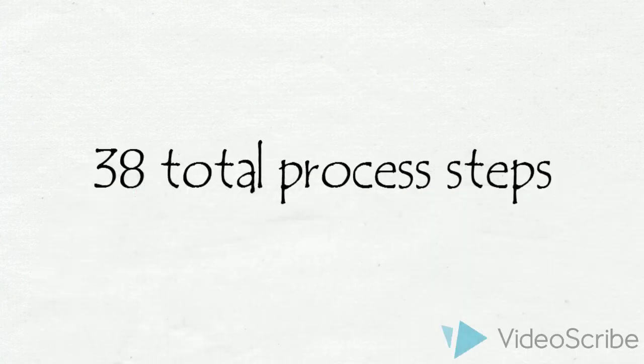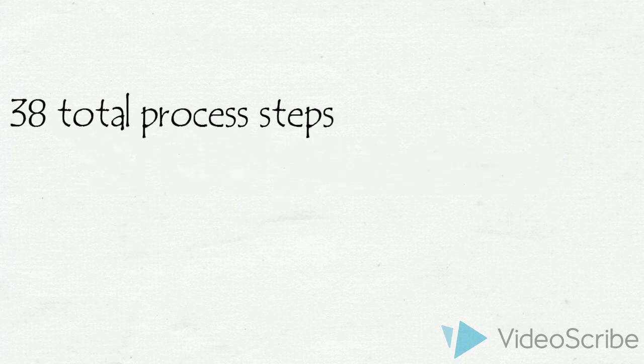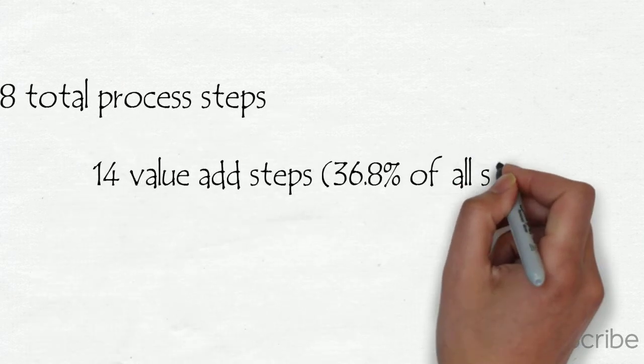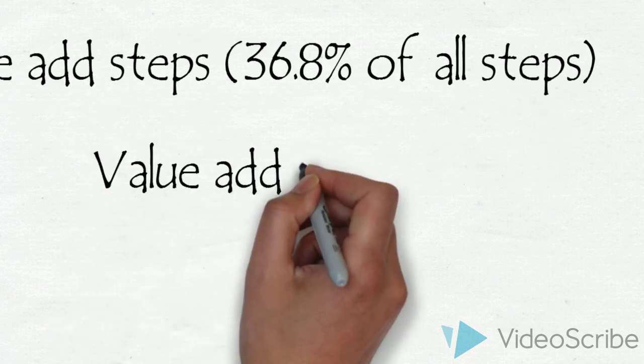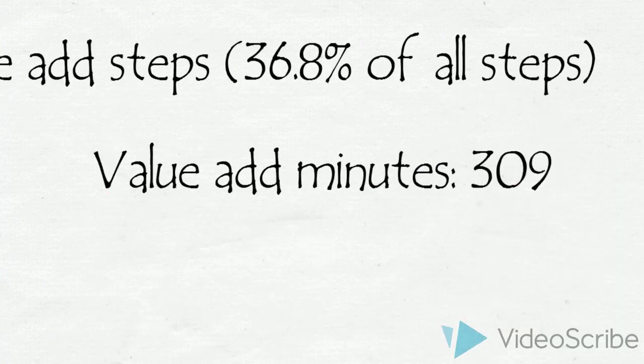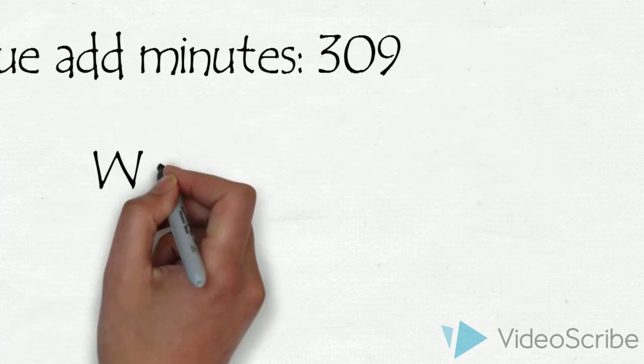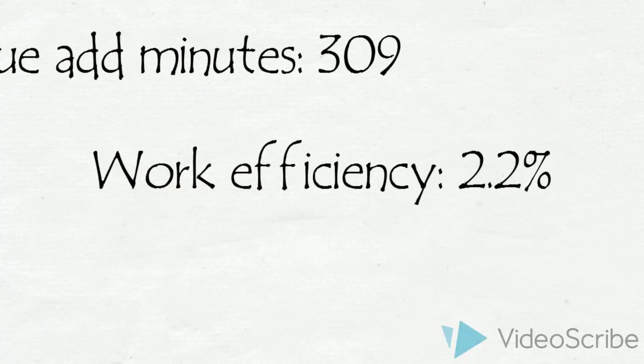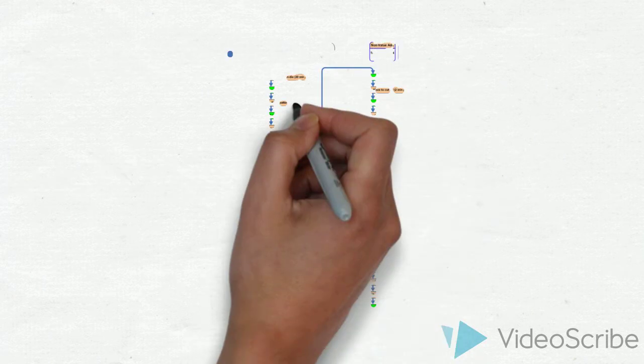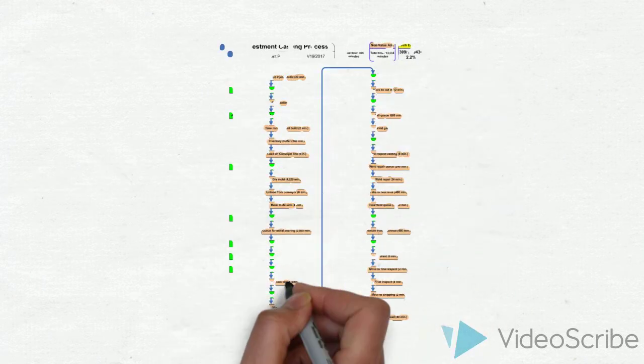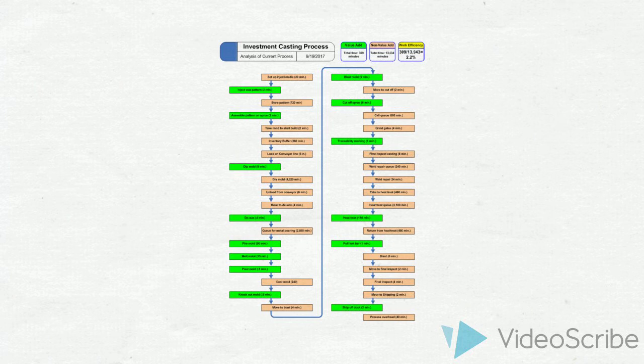Several numbers of importance were generated, including 38 total process steps, 14 of which were value-add at 36.8% of all steps, a total value-add time which was 309 minutes, and work efficiency coming in at 2.2%. With that information segregated, I developed a new flowchart showing the current state steps as value-add or non-value-add.